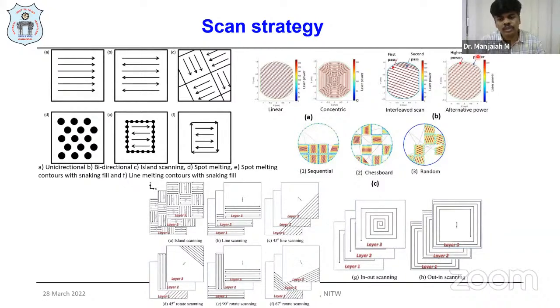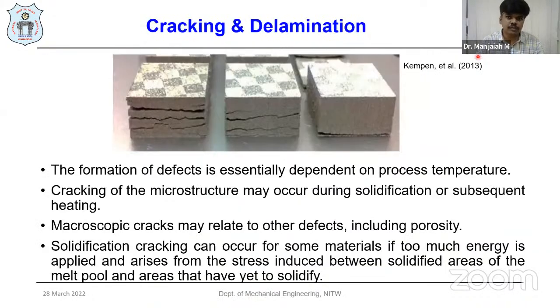It means we have to go with random selection of process strategies depending on the part geometry, as well as trial and error experimentation. The other is cracking and delamination. These kinds of cracks and defects essentially depend on the process parameters. And cracking of the microstructure may occur during the solidification or during subsequent heating and cooling, and it may create some macroscopic cracks. It may be related to other kinds of defects like porosities.